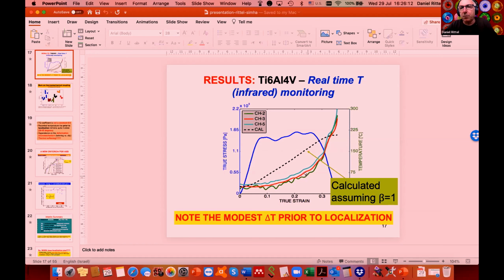And that's in a series of various materials, and it's almost always the same story. So you have two mechanisms, in fact. I'm not saying that there is no thermal softening, but let's say it like that. If you have a material that can recrystallize, it will fail early. If you have a material that is soft, it will go to very large strains, and by doing so, it will generate a lot of heat, and then thermal softening plays a role. So it's a complementary competition between microstructural and thermal softening.